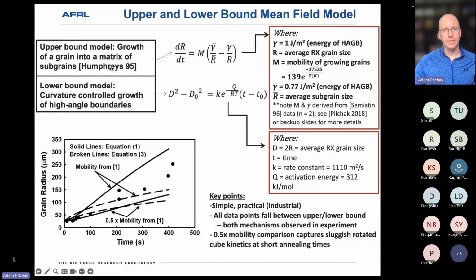So fortunately, in the 90s, Humphreys had caught on to the same thing and developed a relatively simple model to estimate the growth of the recrystallized grains as they grew into the matrix of subgrains and consumed that additional stored strain energy. And then again, after some amount of time, these recrystallized nuclei that were growing eventually impinge on one another, and you transition to more of this curvature controlled grain growth phenomena.